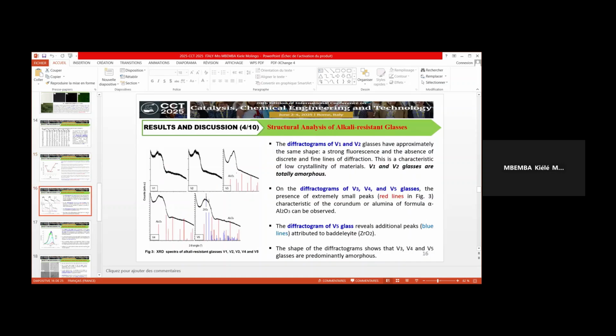Concerning structural analysis, we can see that the diffractograms of V1 and V2 show that the two glasses are totally amorphous. On the diffractograms of V3, V4, and V5, we can see the presence of small peaks, the red lines in figure 3. This is characteristic of alumina. And the diffractogram of V5 glass reveals additional peaks, the blue lines, that are attributed to zirconium oxide.